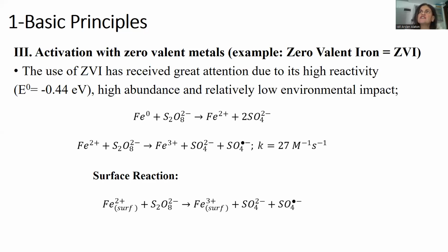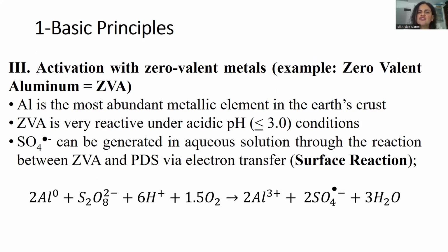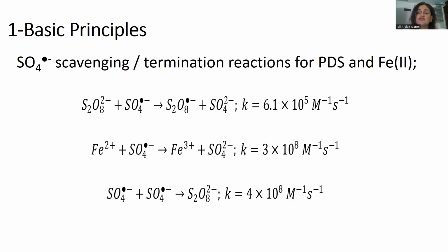So we have fast oxidation of the metal from 0 to +2 to +3, and you probably expect that after some time, because of the high reactivity and fast oxidation, the reaction slows down and is inhibited at the end. We can also have activation with other metals like zero-valent aluminium, which is the most abundant metal element. It's very reactive, but here acidic conditions are very important. The reaction is accelerated at very acidic conditions. Sulfate radicals are formed. Here you see the surface reaction: aluminium is oxidized to aluminium ions, and sulfate radicals are formed under acidic pH values. This can be a very selective and efficient reaction under some circumstances.